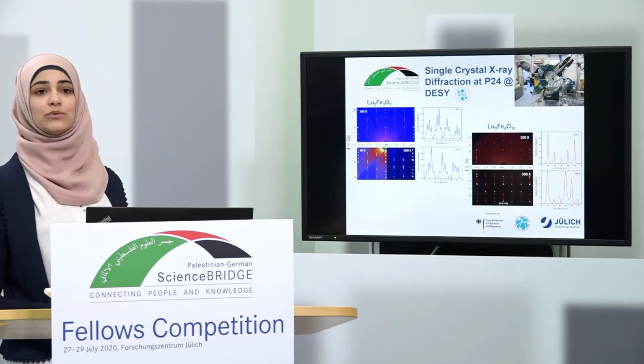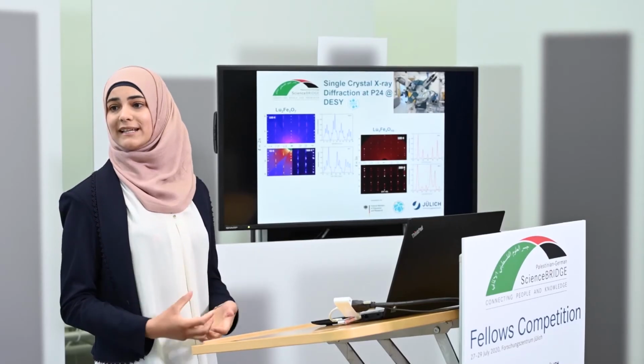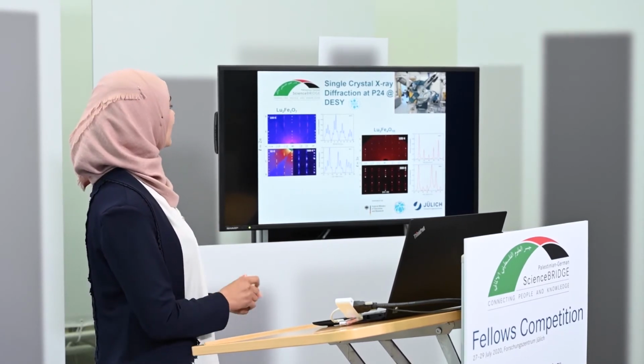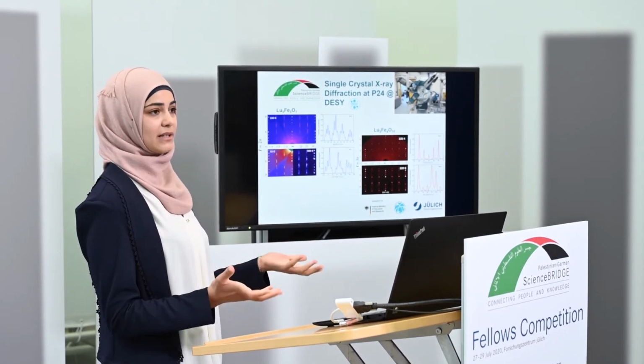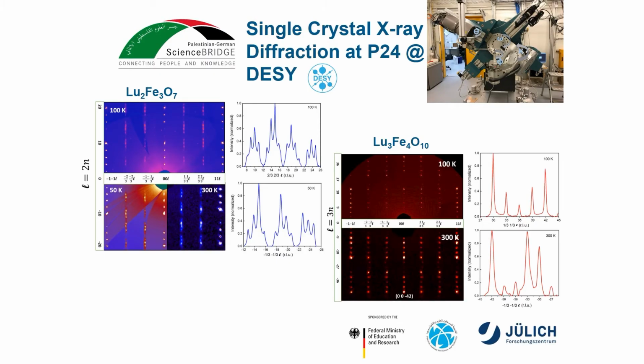Okay, now we want to do a refinement. We want to do single crystal X-ray diffraction, collect the intensities, and afterward decide what type of charge order we have. But unfortunately, we have a problem: the superstructure reflections, when measured at the SuperNova in-house, are close together.